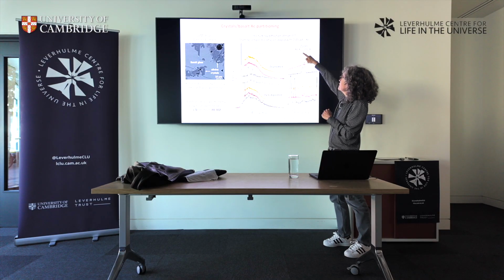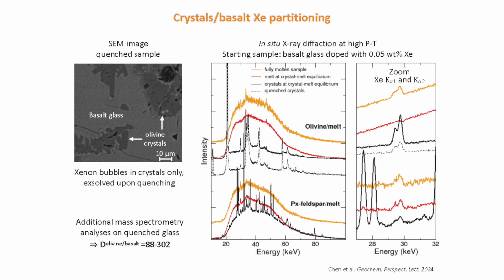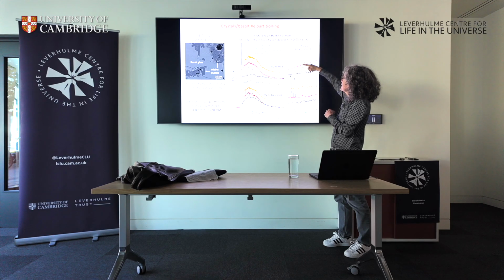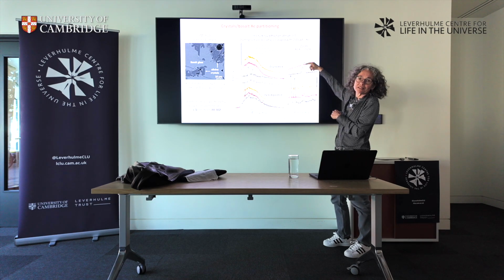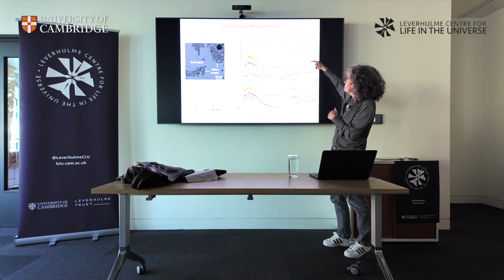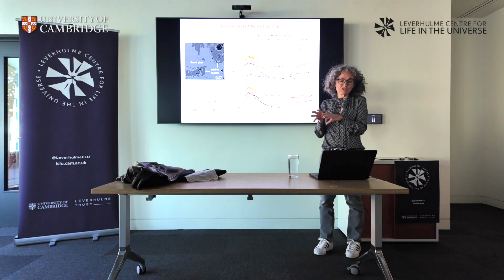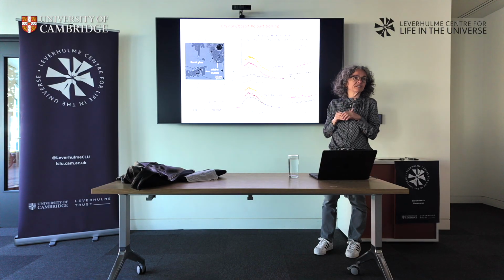So in any case, we start with this glass, we fully melt it, and then we decrease temperature to get equilibrium between the melt and the crystals. And in that case, we couldn't even detect the xenon in the melt. Okay, so we had to recover it and do some mass spectroscopy on the glass. Obviously, xenon was very efficiently sucked by the olivine out of the melt.